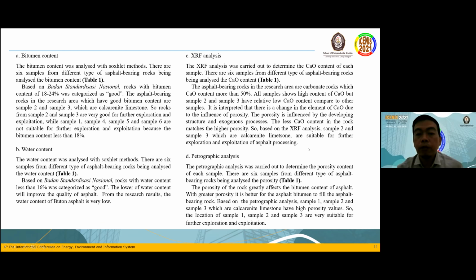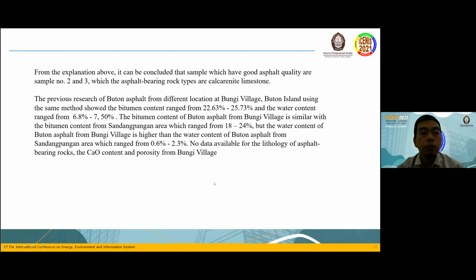Then from petrographic analysis, which aims to determine the porosity of the rocks, the biggest porosity is also in calcarenite limestone, which has high porosity. So from the explanation above, it can be concluded that samples which have good asphalt quality are sample number 2 and number 3, whose asphalt-bearing rock type is calcarenite limestone.